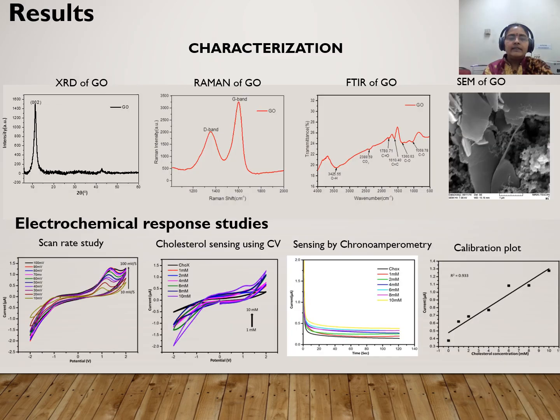Before that, we have characterized the graphene oxide. As graphene oxide was synthesized in the lab, it was characterized using XRD. The peak at around 10 degrees shows the graphene oxide peak, and it is confirmed from this. The Raman studies also show the characteristic peaks, the G band and D band, which further confirms it, and then the FTIR shows different functional groups present in the graphene oxide, showing that the graphene oxide is formed.